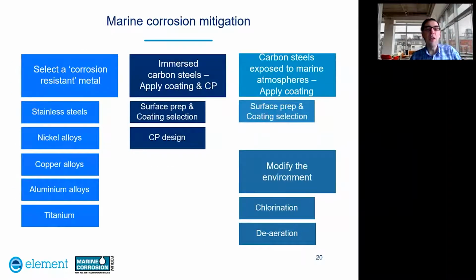So I now want to just say a few words about the mitigation of corrosion in marine environments. So I've split this into 4 areas. The first option is to select a corrosion resistant metal. And the choice in marine environments is normally between stainless steels, nickel alloys, copper alloys, aluminium alloys, or titanium. The other option would be, if using carbon steels in immersed seawater environments, the carbon steel would need to be protected by applying coating and also cathodic protection.